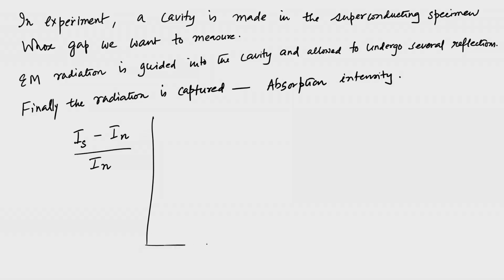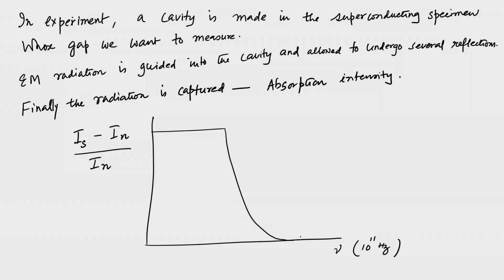And these are the normalized absorption intensities of the superconducting and the normal state. And this is plotted as a function of nu. So, this is nu in units of maybe 10 into 10 to the power 11 hertz and so on. And then what is seen is that the plot, so this is around 5 and this is around maybe 10 and this is 0 and so on. So, this is that intensity, let us say it is in arbitrary units.